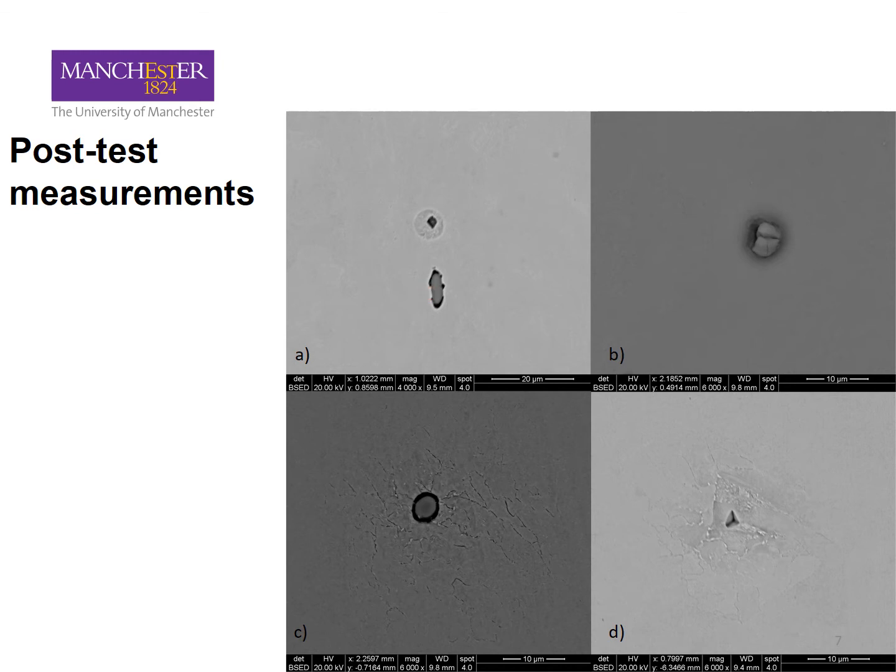Above the particle appears to be a void in what was initially believed to be a region of highly strained material, but we'll come on to that later. Note that the particles in this material are quite large. The scale is 20 microns here. For a more modern, cleaner material, a large particle will be about a micron in size.